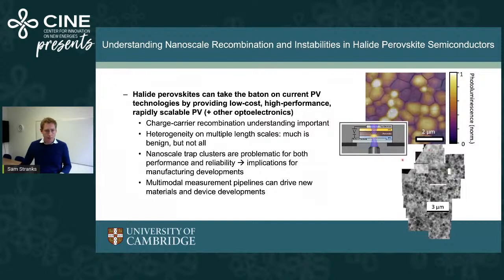So with that, I want to sum up. The halide perovskite technology, we're seeing it can take the baton on the current PV technologies, so it can provide very low cost, high performance, and scalable PV. I've shown a lot about carrier recombination, how important that is. This heterogeneity we see in these materials is also very important. A lot of it's benign, but not all of it. And these nanoscale trap clusters that are problematic, these do need to be ironed out. Even the really small pockets that remain will be problematic for long-term stability.